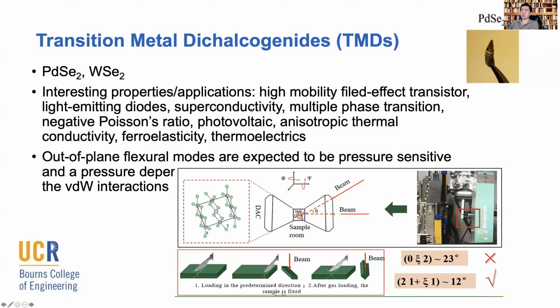As you can imagine, for those 2D van der Waals materials, it's relatively easy to put the stacks, the atomic layers, in the direction perpendicular to the axis of the beam, which means if we look at the material itself, the beam usually comes from the top, and that allows us to probe the phonon dynamics along a certain high symmetry direction in reciprocal space. The problem is, if we want to look at the van der Waals interactions, we usually have to look at the flexural modes, which are the modes propagating out of plane, perpendicular to the basal plane of those atomic layers.